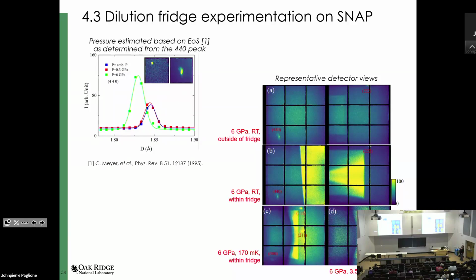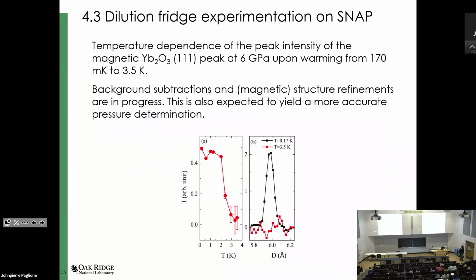But what is the really exciting point here is this peak, because this is actually a magnetic peak. So we were able to see a magnetic peak at 5 to 6 GPa and 170 millikelvin. So we are very excited that this is actually possible. As I said, the detailed analysis is still in process. So here is the intensity evolution of that magnetic peak. It does disappear as we are warming up, so it is a true sample magnetic peak. So yes, we are very excited that it was actually possible to see magnetic peaks at these conditions.